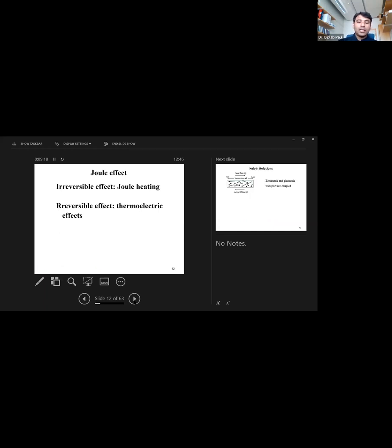So all thermoelectric effects are reversible effects, but any thermoelectric operation is always encountered with an irreversible effect, that is Joule heating, which is killing for thermoelectric efficiency. When the contact resistance between the metal and semiconductor in a thermoelectric device is high, the Joule heating effect can be detrimental for thermoelectric efficiency. So special care needs to be taken when making contacts in real modules.